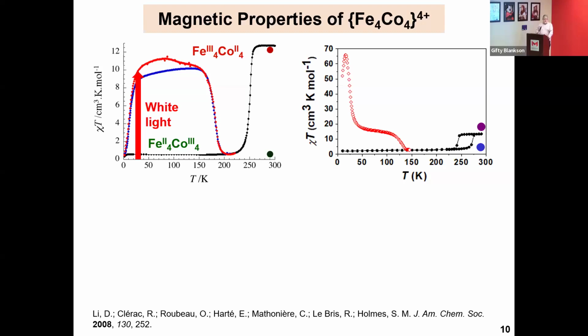Comparing that to the three-dimensional Prussian blue, we don't see long-range magnetic order because these are molecules. They have 8 spin centers as opposed to millions. We do see that paramagnetic state. The spins are schizophrenic and barely talking to each other. And that mirrors what you see at high temperature in terms of its magnetic signal.